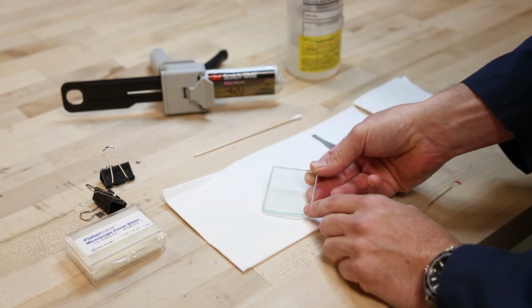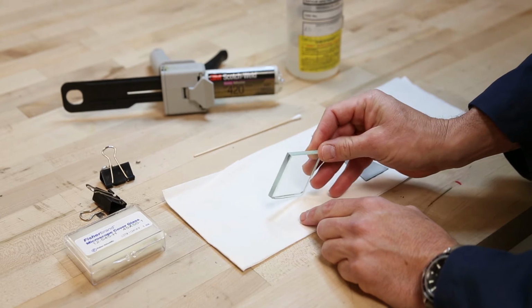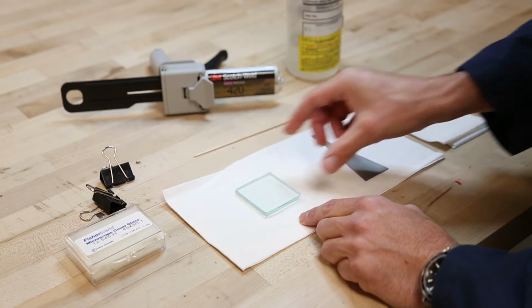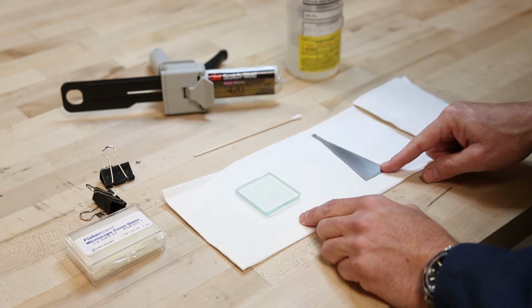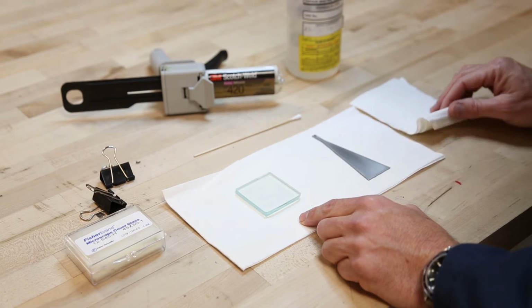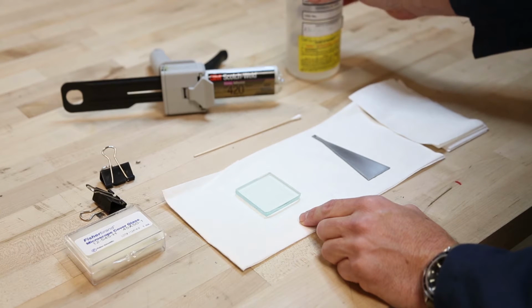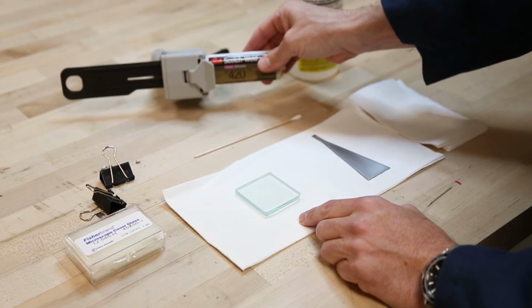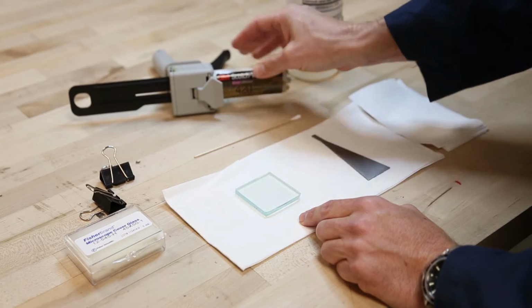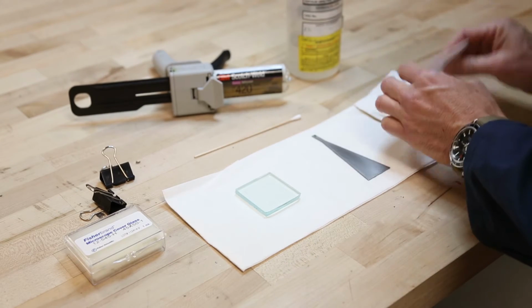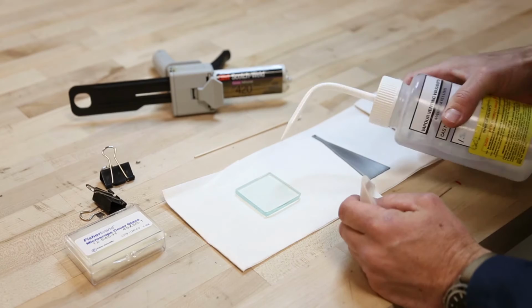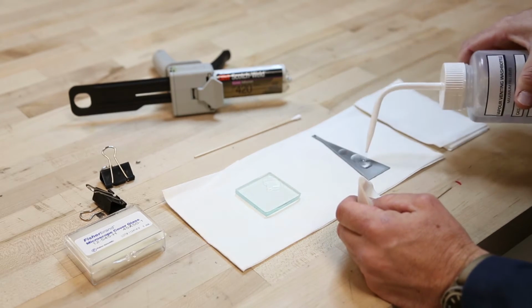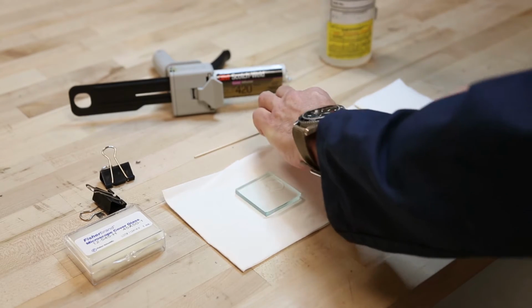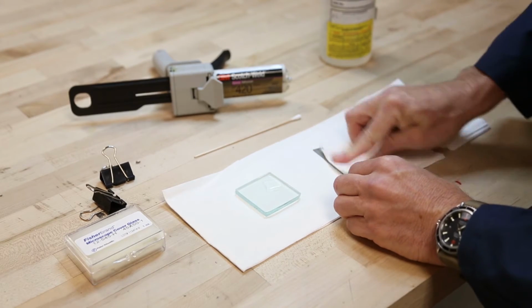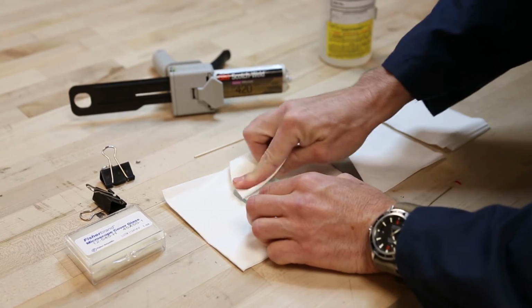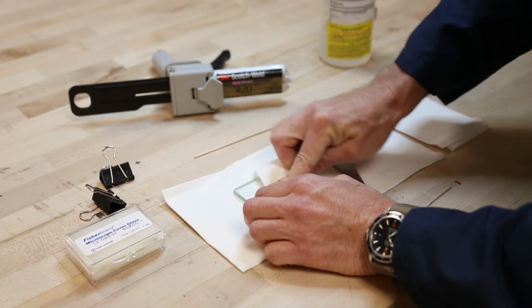It looks almost identical. I know it's hard to see, but that thin microscope slide is now laminated to this slide of glass. And to prepare the sample, again, I have a titanium tapered beam, some clean towels and IPA for cleaning, a cotton swab, and the DP 420 epoxy, along with a couple binder clips. So, real similar to all the other sample preparation processes, I'll use IPA to clean both the beam and whatever the coupon is.